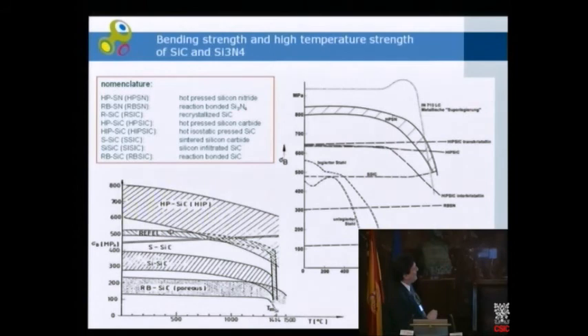Silicon infiltrated silicon carbide. One handicap, we must stay at a safe distance from the melting point of the silicon. That was the ultra fine-grained material developed in Harwell by our British colleagues for their nuclear power plants. At the time, it was the finest silicon carbide material that was reaction bonded or siliconized. And the advantage in mechanical strength was quite impressive. The question was, can one or two or more of these materials be processed in the shape of a high precision tube?